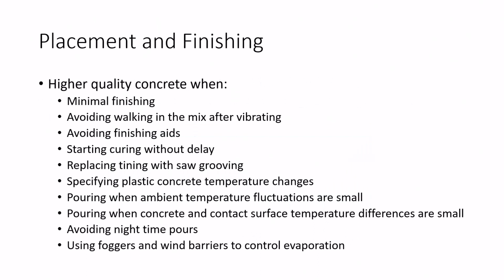The scan also discussed placement and finishing. So it's not really innovation, but most DOTs agreed that you do get the best quality concrete when you minimize finishing. So the big thing is to start external curing, or wet curing, right away. They even discussed bringing work bridges to the site so that workers can start curing right away, avoiding tining and instead saw grooving the hardened concrete so that you can start that external curing sooner.